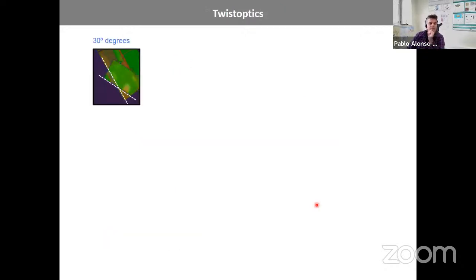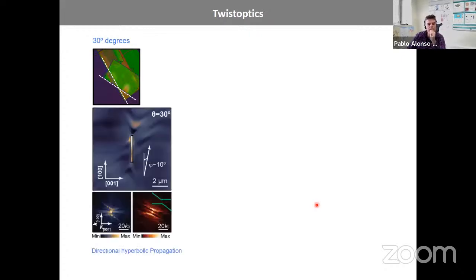Then we just fabricated the samples. It was quite easy: just take one flake and then rotate the other. In this case, we don't need super small twist angles like in graphene, like 1 degree or so. Here with 30 degrees, we see huge changes in the propagation, as I'm going to show you now. So we did a 30 degree difference between the two layers, and we used an antenna instead of the tip of the SNOM in this case to see the propagation.